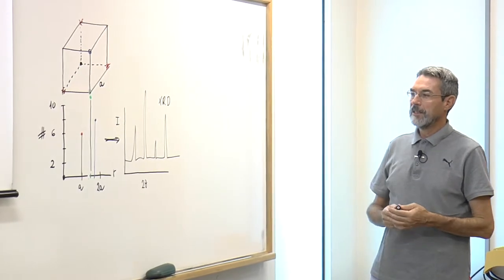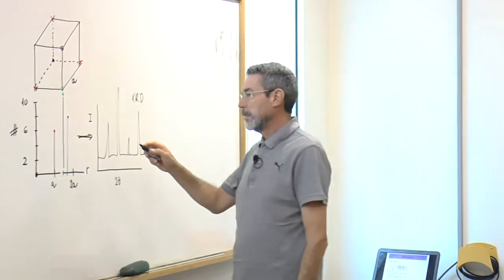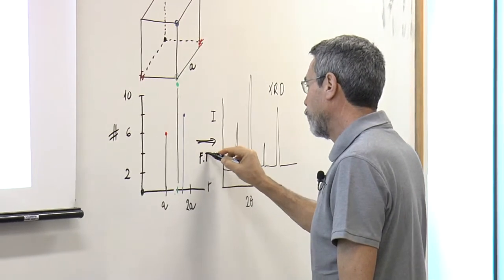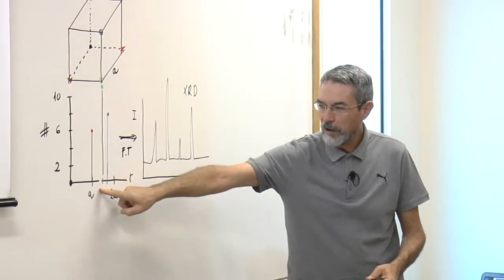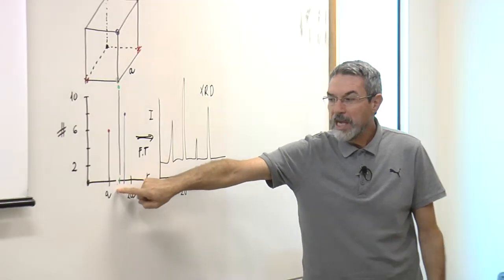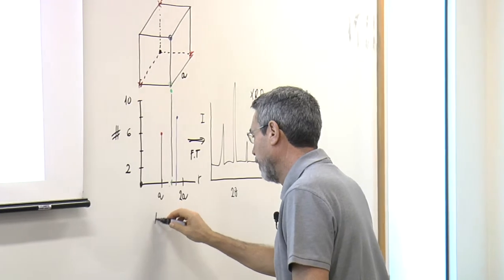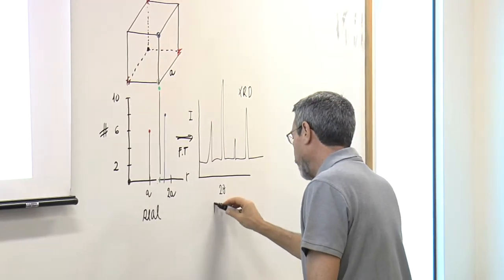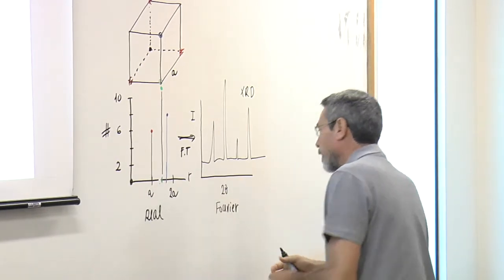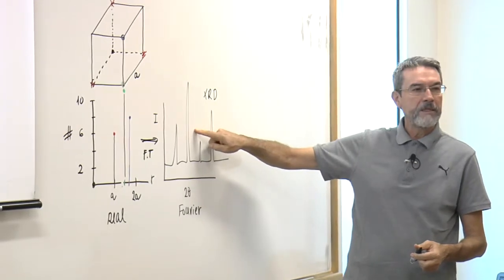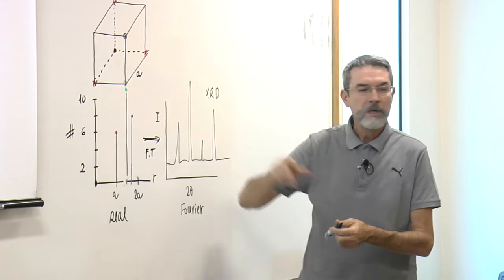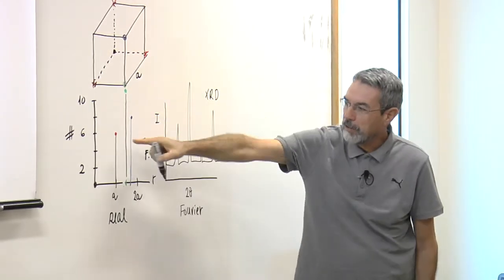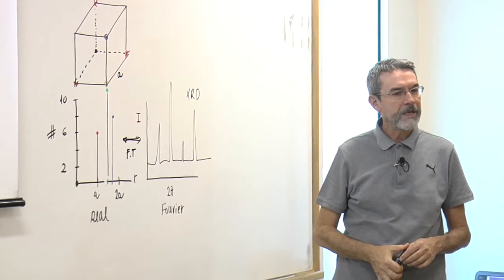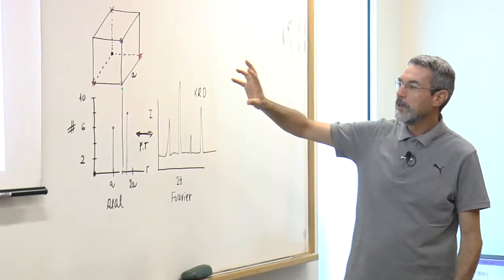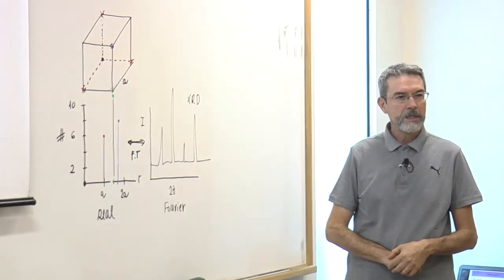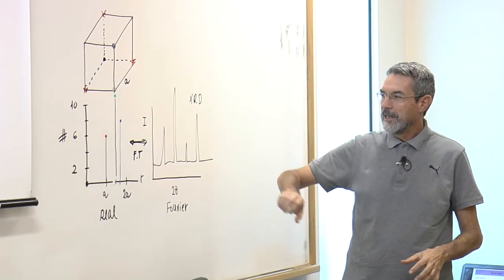The nice thing is that if you do a mathematical operation, a Fourier transform of this spectrum, this is the real space of the crystal, and this is the Fourier space. A Fourier transform will give you this, and vice versa. A Fourier transform of this will give information about the real space. Just a mathematical operation. And that's what people use to grasp information about the structure. Just a Fourier transform. This is fine for crystals.